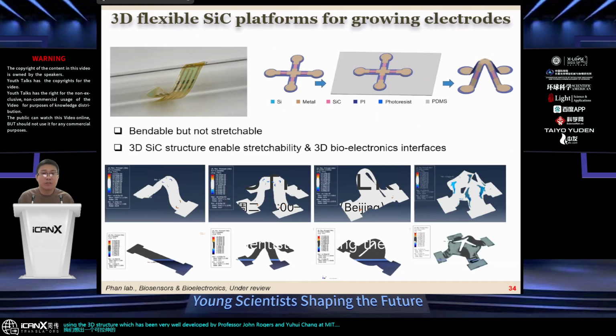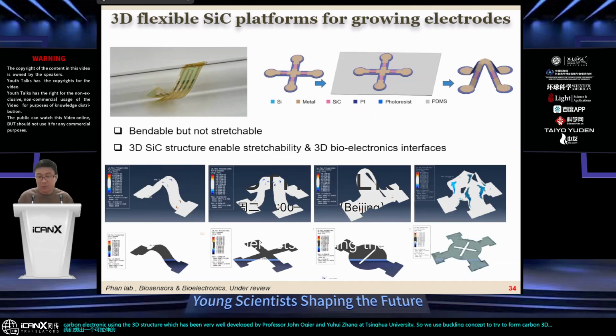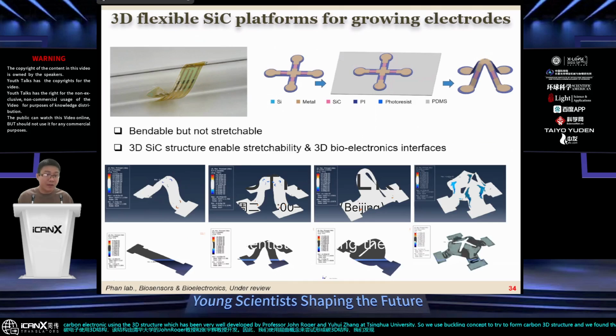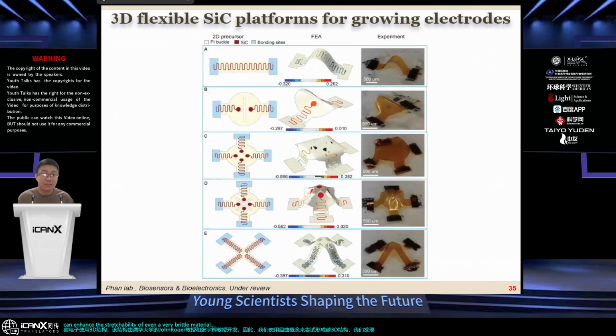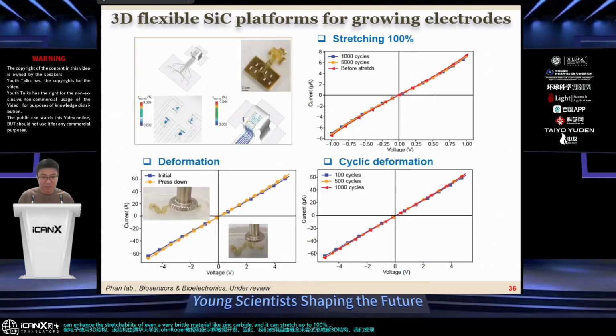So we use the buckling concept to form a silicon carbide 3D structure, and we found that this structure can enhance the stretchability of even a very brittle material like silicon carbide, and it can stretch up to 100%. It can deform without any significant change in the electrical